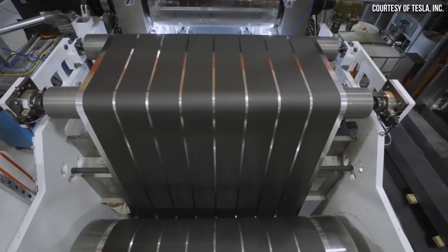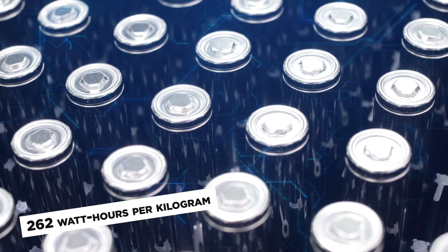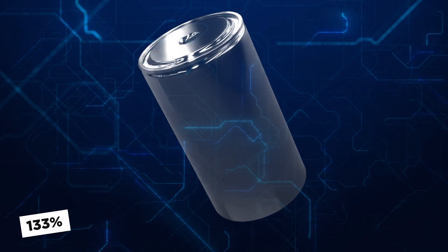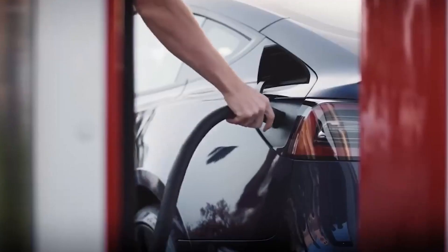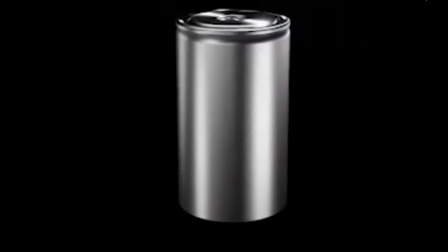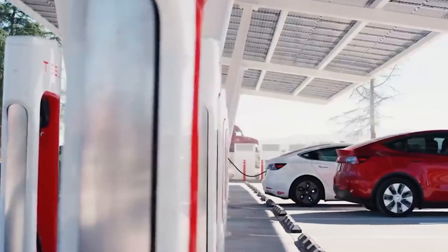To put this into perspective, the more common Panasonic-made 2170 cells in the Model Y Long Range have an energy density of 262 watt-hours per kilogram, meaning the new 4680 cells have notably less energy density than these Panasonic cells. Early adopters of 4680-powered Model Ys also report that these cars tend to charge more slowly, with the 4680 battery packs not drawing the full 250 kilowatt power from V3 Supercharger stalls, instead quickly throttling down to a lower level.